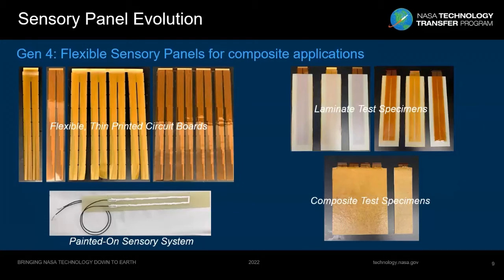And so we decided to also look at something not just a laminate version where you could adhere a prefabricated thin flexible circuit board with conductive traces to the structure. We could actually print this onto the surface. And so we made a version, and there were stencils used to apply a conductive silver paint to a surface. And then leads were attached, and this was primarily used to monitor for cracking in an existing structure. Next slide.